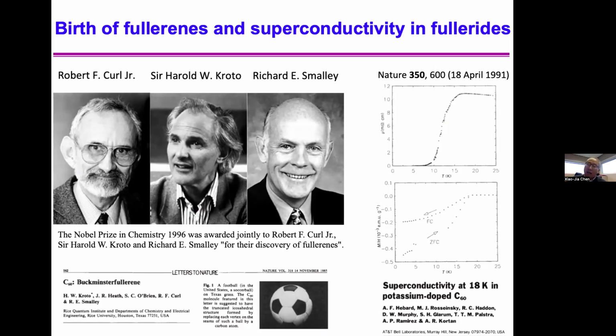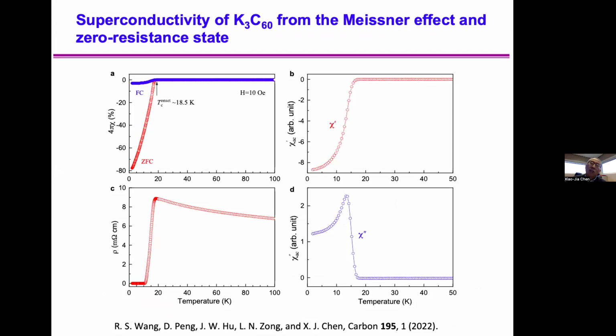At that time, I would like to mention their measurement was not done on the same material. For the resistivity, they used the film, but for the susceptibility they measured bulk material. This is the measurement supporting the two characters of superconductivity from two samples. We are the only group in the world to reach two characters supporting superconductivity from the same material.